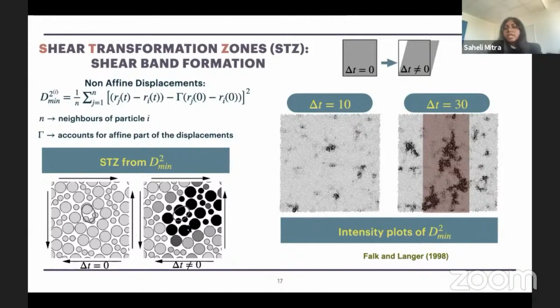This kind of zone of particles that are taking part in plastic rearrangements because of shear is called a shear transformation zone, and they play a role in the formation of the shear band. To understand how, we can look at the illustration on the right, where we are plotting the intensity of D square minimum at two different time steps. Initially, these STZs are localized and scattered all over the place, but with time, they correlate in the formation of the shear band.